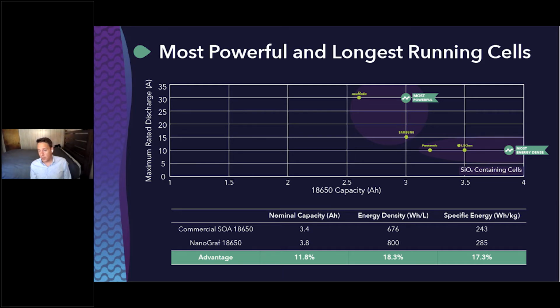And I think what we're most proud of, and I think there'll be a press release here in the next few weeks about this achievement, is the fact that we've been able to make the most energy dense 18650 cell. It's a 3.8 amp hour energy cell. Again, if you take a look at state-of-the-art cells from Panasonic and even LG Chem, the highest that's really achievable right now is 3.5 amp hours. And so we've been able to demonstrate just in one shot an 11 to 12% increase in nominal capacity. We've been able to achieve that 800 watt hour per liter energy density threshold as well.